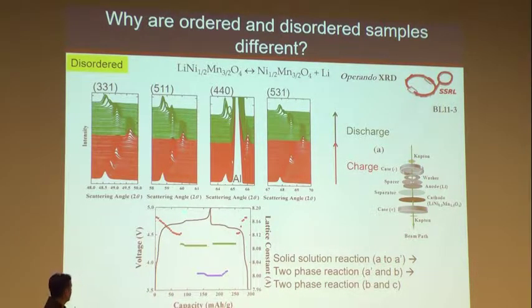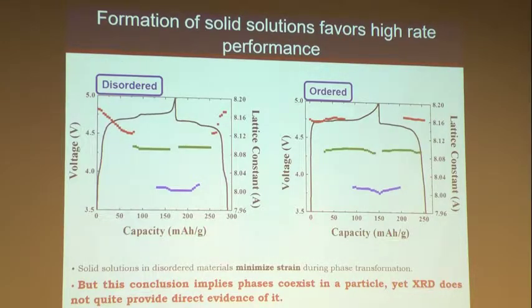This is the voltage gap that I was just talking to you about. This separation between two plateaus gets smaller when your material gets ordered. And so this is a disordered material that I'm showing you here. What does an ordered material look like? Well, if you plot the same cell parameter information for the ordered material, first of all, you see this decrease in the voltage gap. It's the same kind of plot, and now your two plateaus are much closer. And now you see that the initial solid solution region has disappeared. And you have a significant difference in lattice parameter between the first phase and the second phase, much bigger than here.